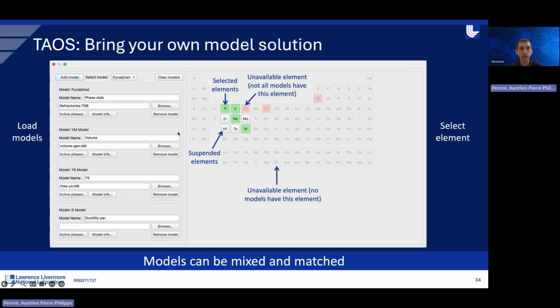And as you are progressively loading these models, you will populate this periodic table. So how does it work? You can select the elements that are available in all models. So I selected, for instance, here 4 elements: titanium, vanadium, niobium, tungsten. Again, this is just an example. Could have selected more or less. And the elements that are here in red are elements that are considered by some models, but not all of them. So you cannot really use them for your optimization. So really the takeaway is that now you can mix and match different models.